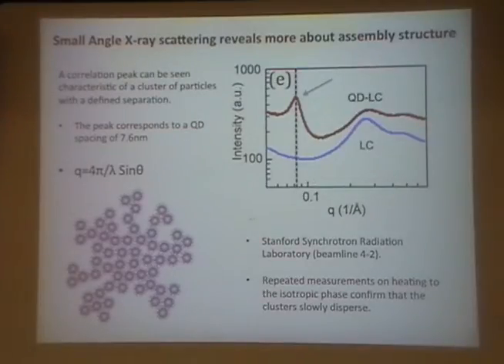We can confirm the dispersion of the particles as well by heating. If we do this measurement and then we heat into the isotropic phase, then this peak goes away. But it takes some time. We can see initially it's still there, and then we do repeated scans. Eventually, the peak sort of goes away as the cluster disperses out. So it's another confirmation of that kind of idea. So this is a rough idea of what the structure should be like.